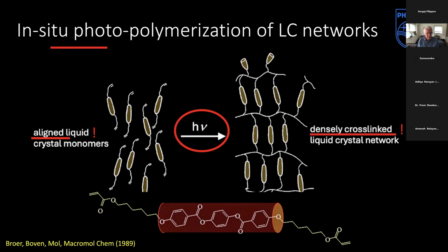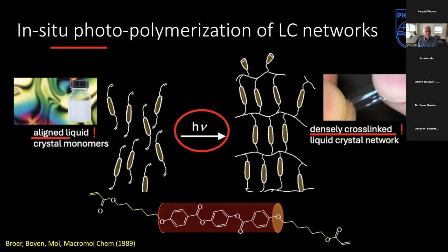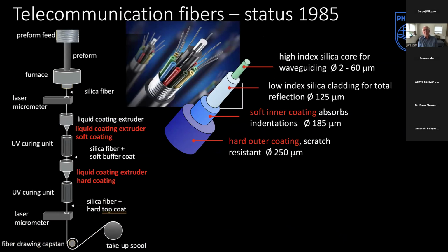So this is the first monomer that we synthesized for that purpose, and indeed you could convert it from the liquid crystalline state to the densely cross-linked liquid crystal network with a relatively high strength and optical anisotropy. Well, I was working at that time for Philips Research, and there was a reason why we developed that material, and that was the application in optical telecommunication fibers.